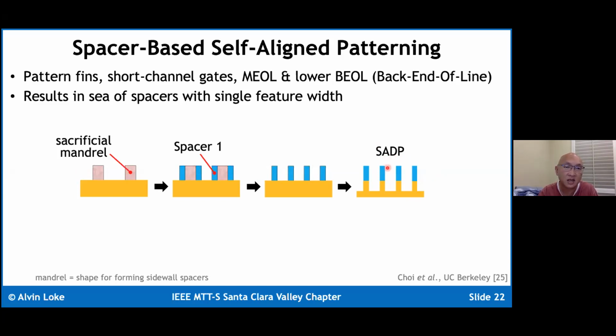Now there's a limitation to this single self-aligned double patterning approach, as it's sometimes referred to. The problem is if your pitch limit here is say 80 nanometers, you can't have a pitch tighter than 40 nanometers. Here we are way past the point of fin pitches that are less than 40 nanometers.